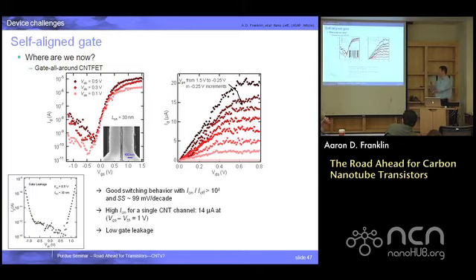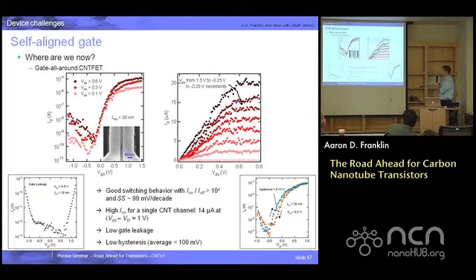Another thing I don't have a lot of time for, but anyone who knows the field would be curious why this thing is an NFET, because it has palladium contacts, and yet it's a really true NFET. And there are really good explanations for this now after we've done some further device work on it. But it does look like a good device from the general perspective in terms of on current and switching behavior, with the need for improvements in the dielectric still, because we're just using an as-deposited ALD film. There's no annealing to eliminate the charge issues in the dielectric. So based upon those non-idealities, it performs very well.